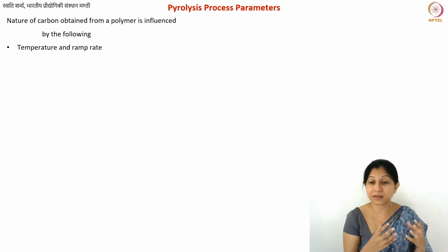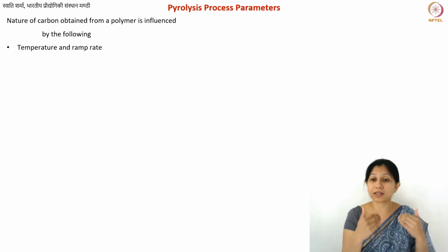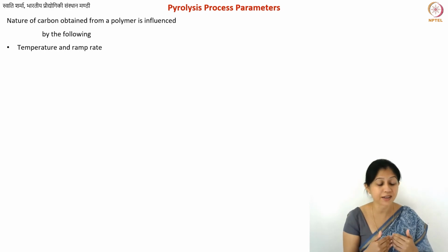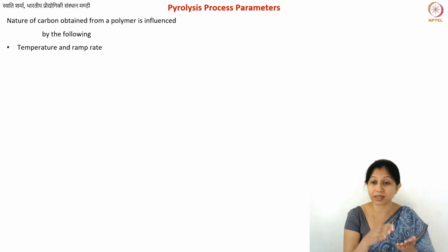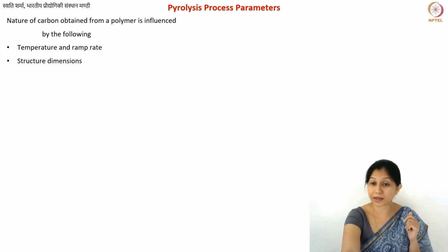So they will then end up participating in secondary reactions, or they may end up redepositing on top of your material. In fact, whether you perform pyrolysis inside a closed container or an open container makes a lot of difference, because there is this redeposition or reparticipation of the byproducts in your reaction. So all of these things will definitely make a difference.